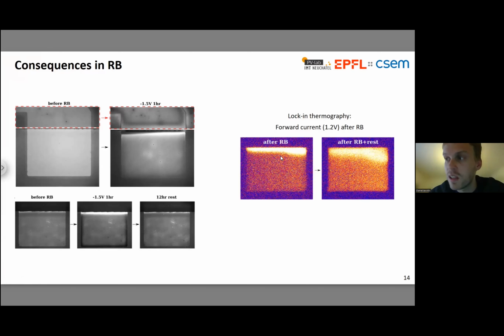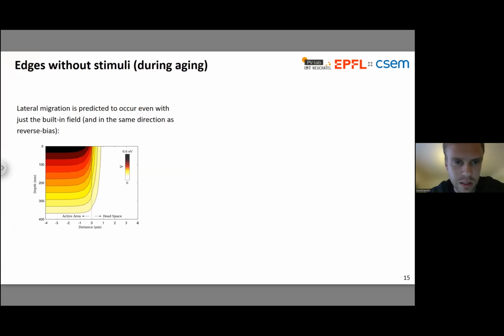And we know for a good solar cell, we don't want a lot of current passing in forward bias. We'd like the forward current to be as small as possible. So this enhanced current injection in forward bias is not a good thing to see. And this might be responsible for the fact that often when we reverse bias our devices, we see that their performance drops. But if we leave them to rest for long enough, in particular, for our devices, it's often overnight periods of 24 hours or more, they typically recover their performance. So that could be associated with this kind of intense migration happening at the boundaries, which is affecting current injection, and then that process relaxing over time as you allow the device to rest. Okay, so it's not without its consequences.